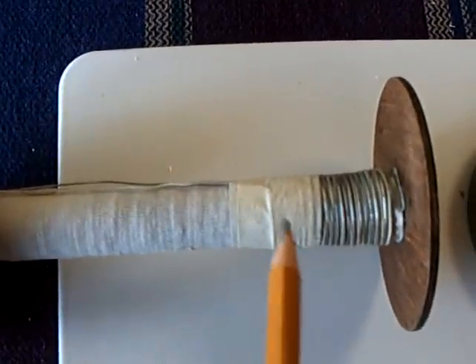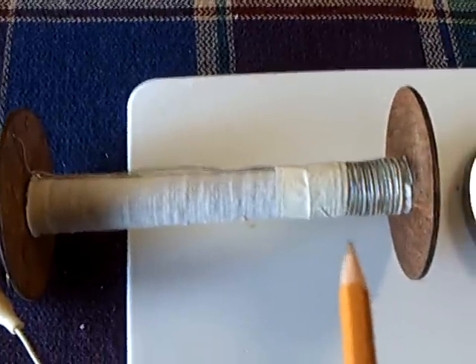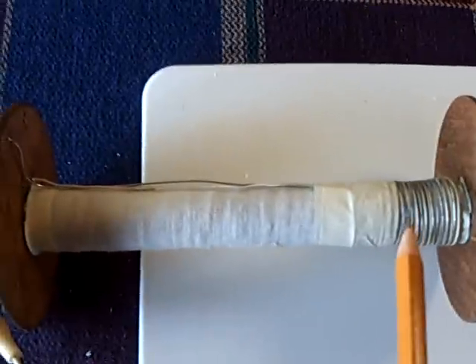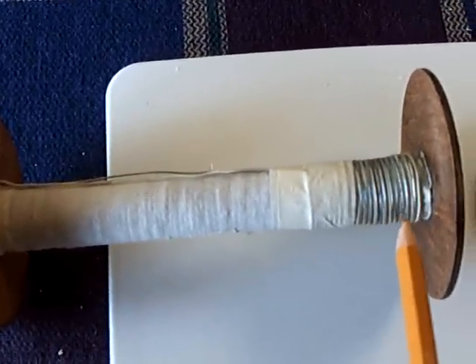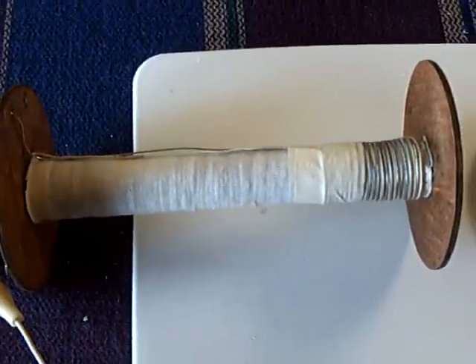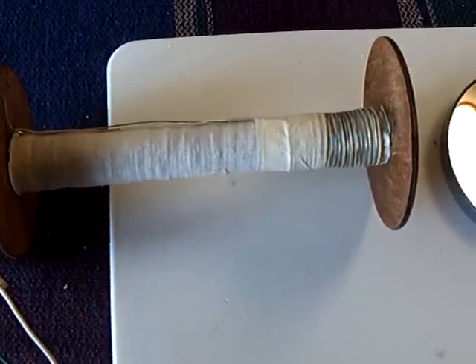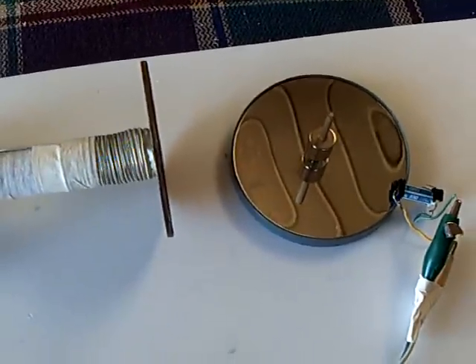Like I say, this coil is not finished at all. And the reason I'm not going any further with this is because this will stop. This galvanic action breaks down the zinc on that steel wire, and as soon as that happens, this goes down to about 0.3 volts at about 10 milliamps, and it won't run anything that I've found.